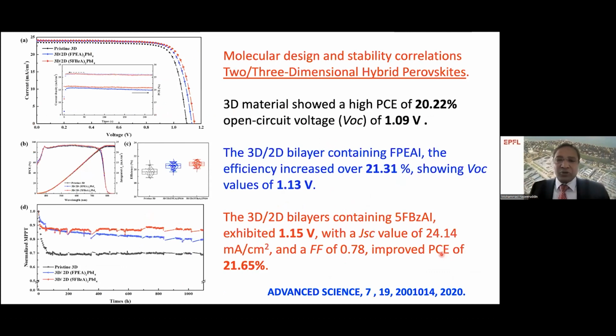So what does it give you having this type of two-dimensional perovskite on top of three-dimensional perovskite? The best way to compare this material is photovoltaic properties and stability. Now, if you look at the reference sample, our reference sample has only 20% efficiency with a VOC of 1.09. By depositing two-dimensional perovskite, that's a fluorophenylethylamine-containing cation,